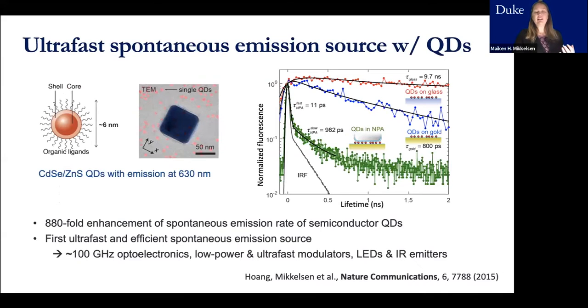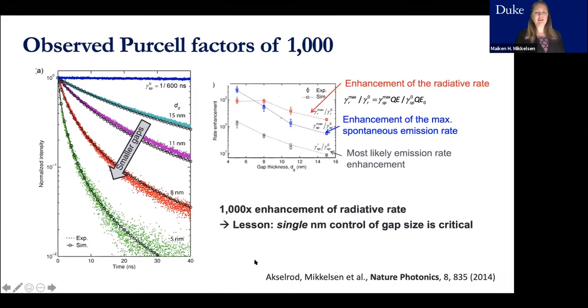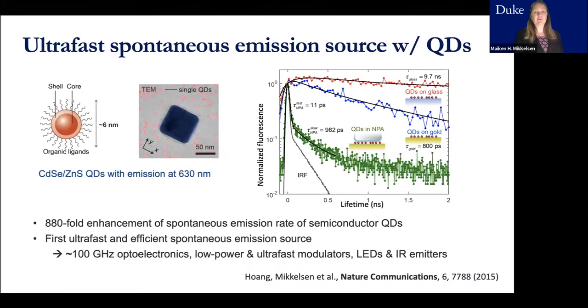You may notice that even if I had these large enhancements in the spontaneous emission rate, we're still not really getting to ultra fast speeds, because this is still tens of nanoseconds, because we started out with such a slow emitter, which we did to be able to map out these large enhancements and not hit the instrument response function time limits. So next we looked at colloidal cadmium selenide zinc sulfide quantum dots.